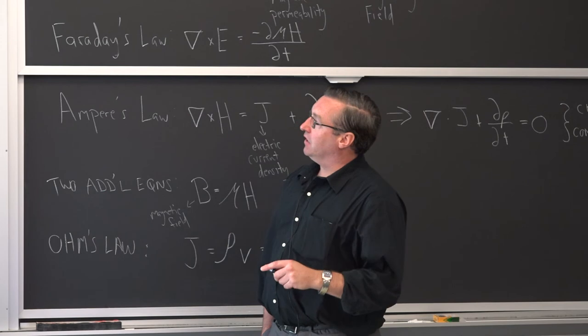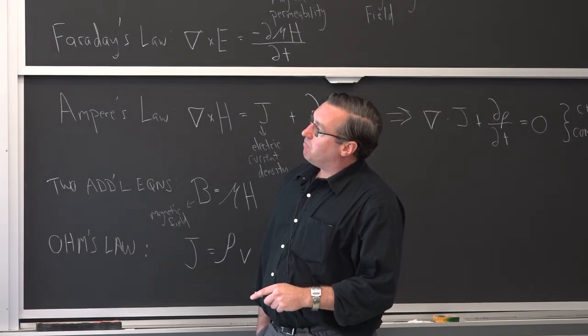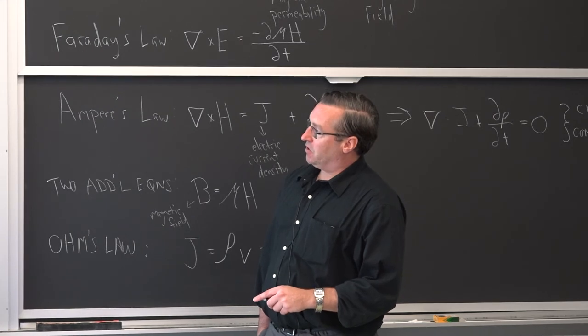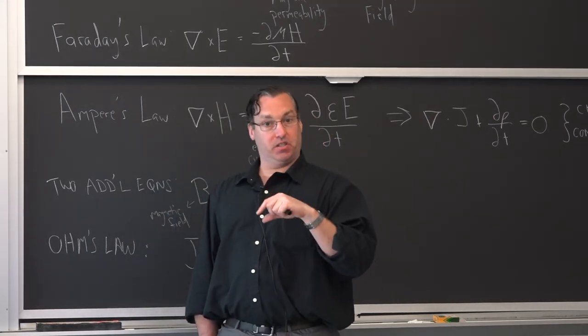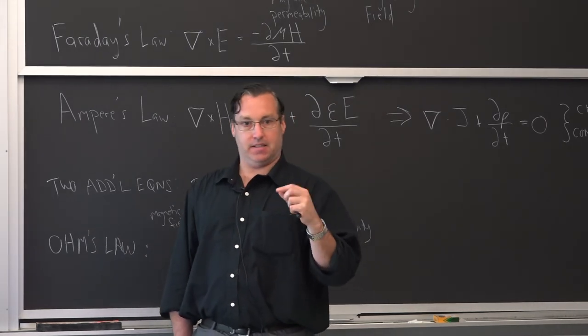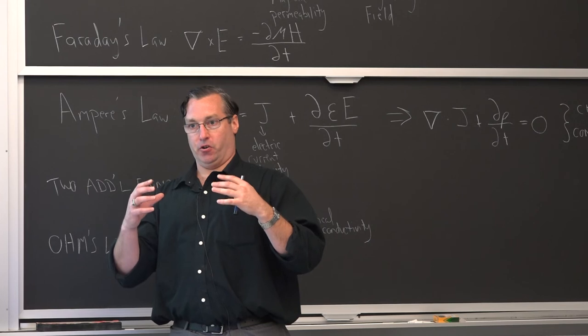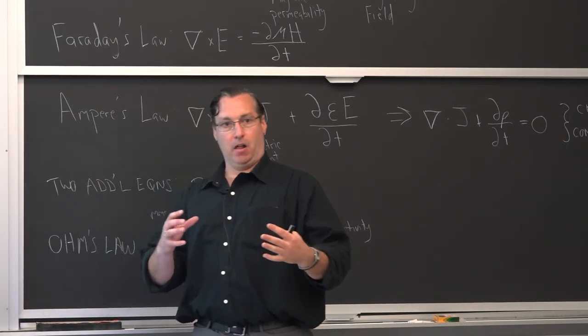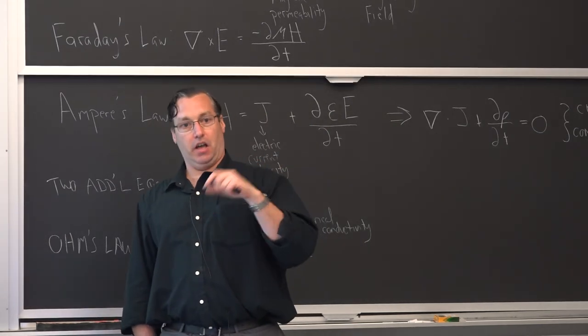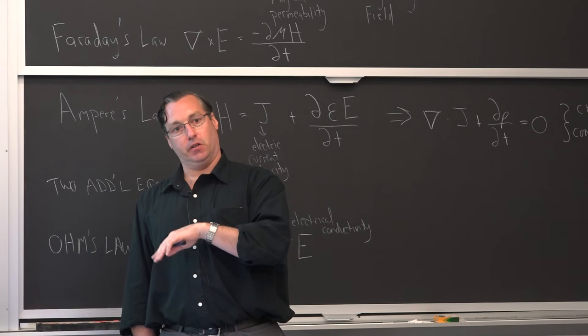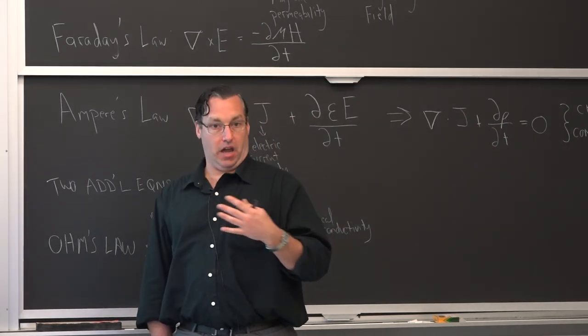The percent IACS conductivity varies based on the material being tested — there are a couple orders of magnitude range depending on the material. Waspaloy and Hastelloy are highly alloyed materials — a nickel-based superalloy can have eight to ten trace elements added to achieve mechanical properties, and this ties into microstructural noise. Titanium alloys are highly noisy, aluminum alloys have noise, and the alloying affects that percent conductivity. Similar to the ultrasonic lecture where acoustic waves scatter through material, here it's how electric or magnetic waves scatter through the material.